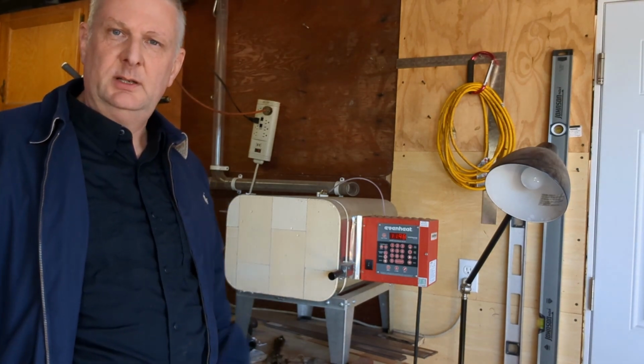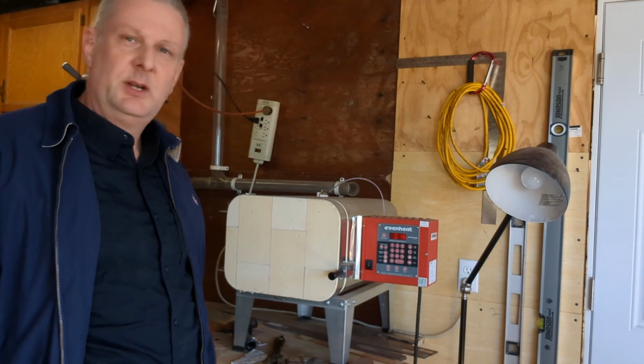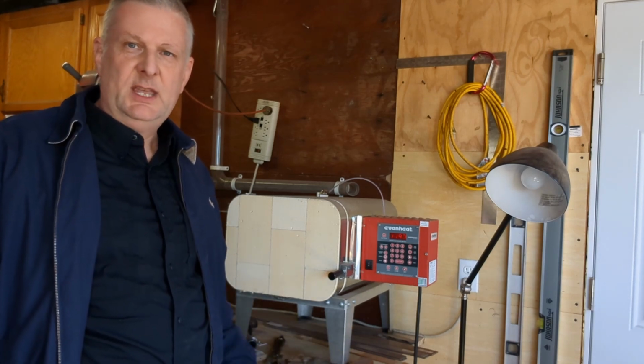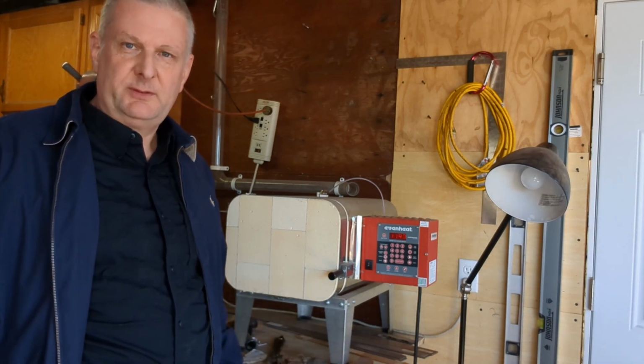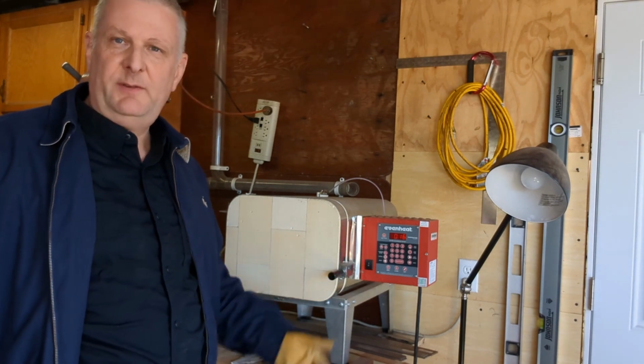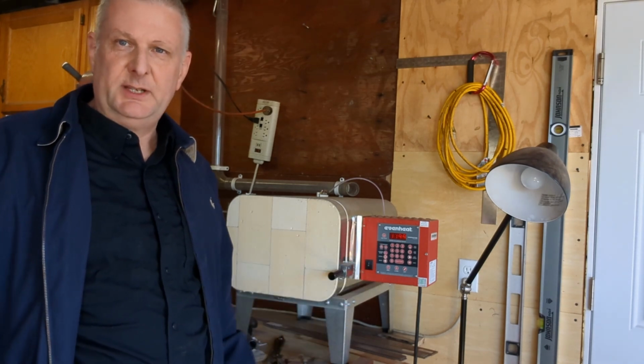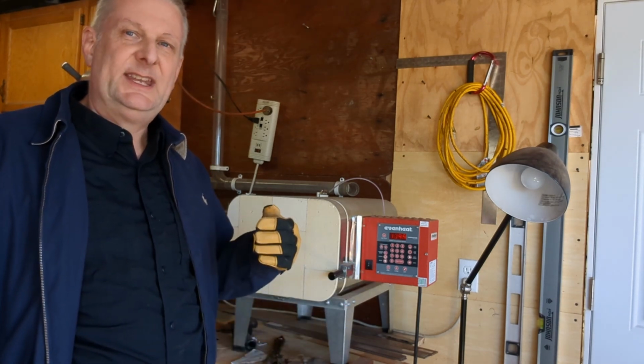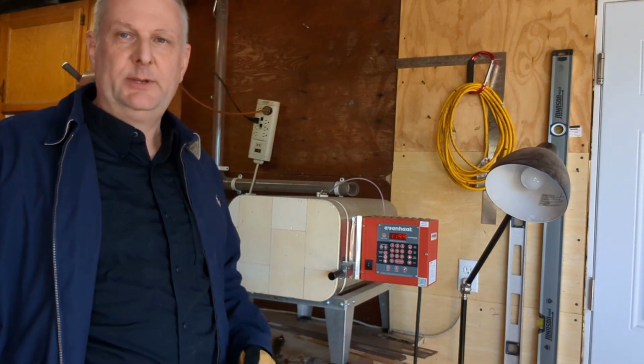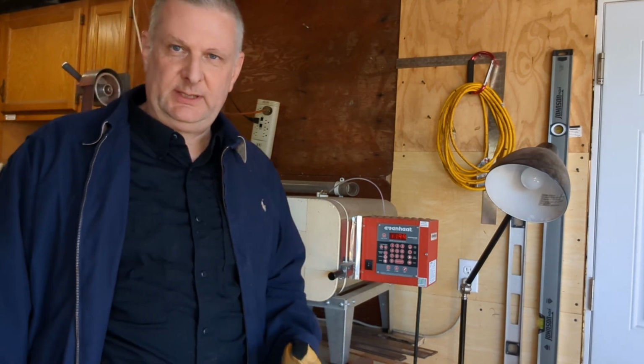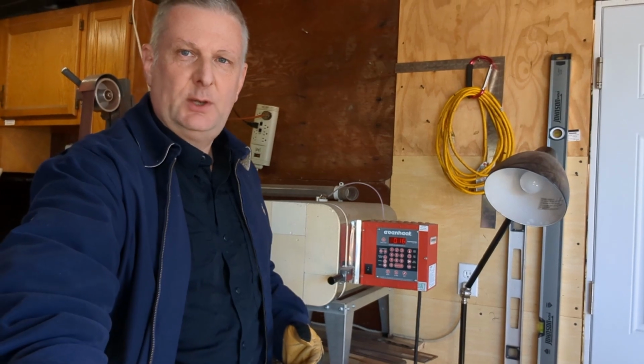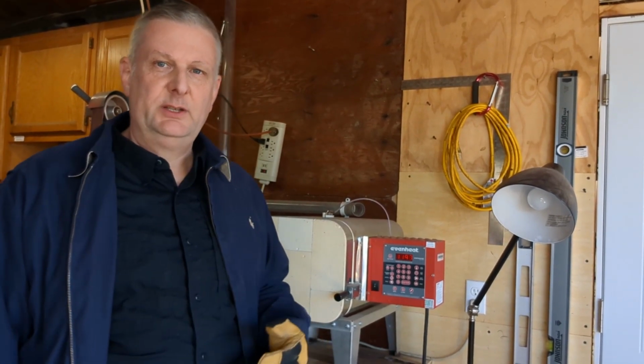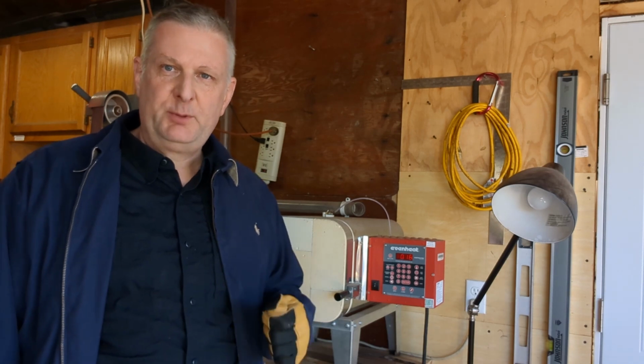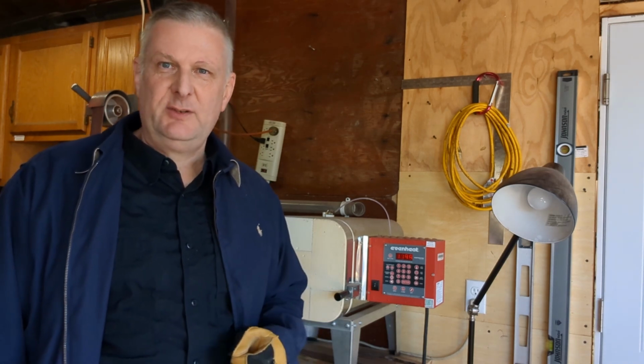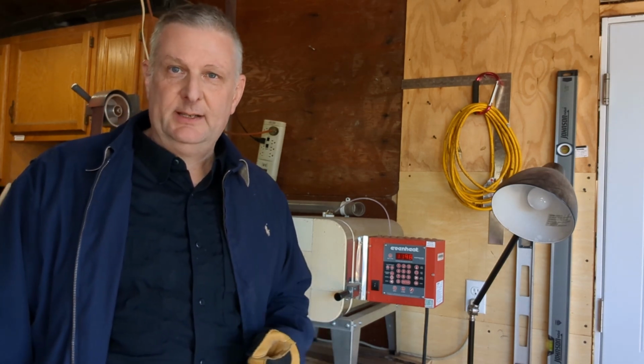So this thing will hold a precise temperature within 3 or 4 degrees. It'll hold 1200 or 1475 just within a couple of degrees, so I can get an exact and repeatable heat treat. And that's the key when you're doing this stuff. I mean, you can do this stuff the old-fashioned way, and that's all well and good, but if you can take a steel like O1 and give it a very precise heat treat, give it the exact heat treat that it needs, you get a better blade when you're done.